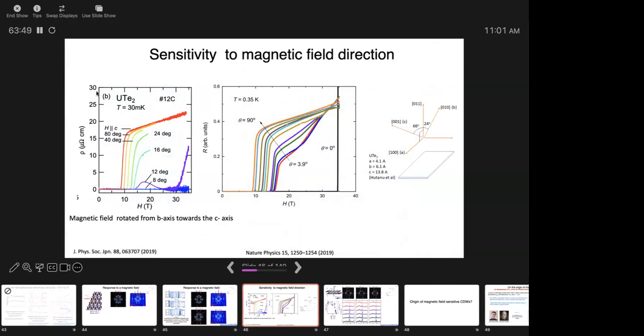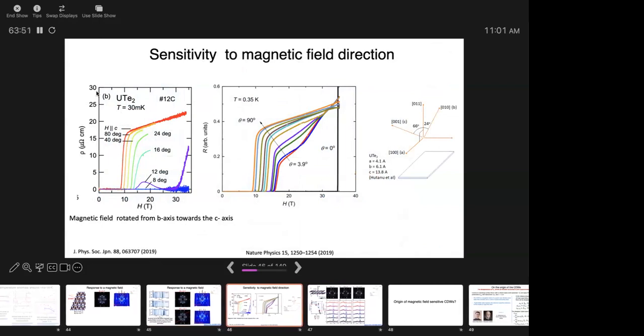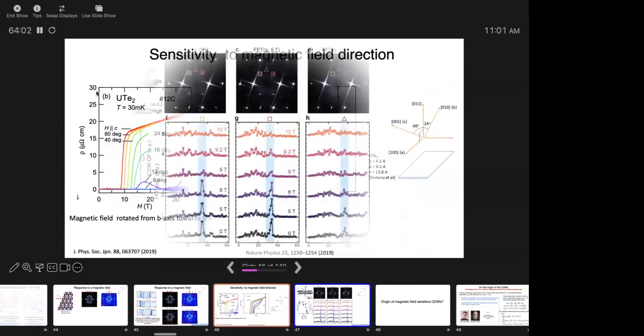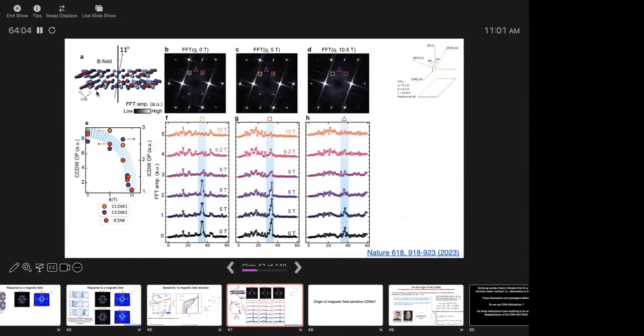So you know that the sample is extremely sensitive to magnetic field. A few degrees off from 24 degrees, HC2 changes a lot. So this was just fortuitous. We happened to cleave the sample such that it was at 11 degrees away from our previous sample. And now you see that at this 11-degree angle, HC2 is much smaller.